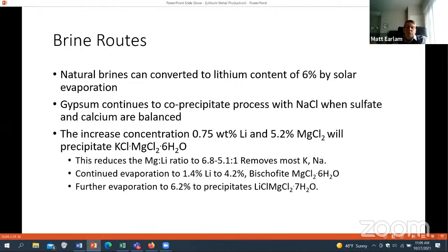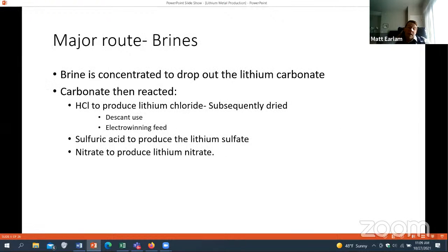So as you reduce, most of the potassium and sodium are removed, and then you continue to evaporate, and you get to about 4.2% lithium chloride in a magnesium chloride, lithium chloride solution. Further evaporation gets you about 6.2%, and at this point you precipitate out the equivalent lithium carnallite, which is similar to the potassium carnallite that precipitated earlier. Then you react this with sodium carbonate, and the sodium carbonate will drop out lithium carbonate as a solid. As I said before, it doesn't have a lot of waters of hydration. It doesn't have any waters of hydration, actually. So it's pretty easy to separate. You can separate it by filtration and then crude drying just to produce the lithium carbonate.